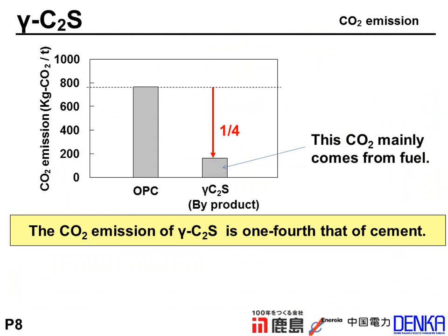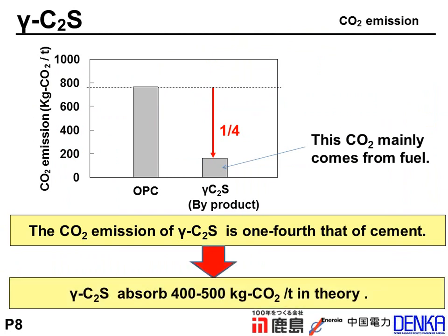This figure is the comparison of carbon dioxide emission of ordinary Portland cement and gamma C2S. The value of ordinary Portland cement is around 800 kg CO2 per ton. On the other hand, the value of gamma C2S is below 200 kg, so it's 1/4 of ordinary Portland cement. This 200 kg of CO2 mainly comes from the fuel in calcination. On the other hand, gamma C2S absorbs 400 to 500 kg CO2 per ton theoretically, so it contributes to the reduction of carbon dioxide.